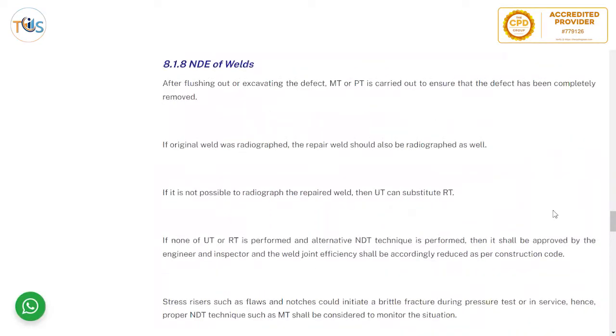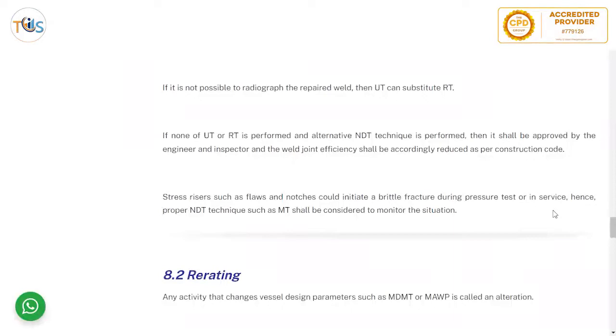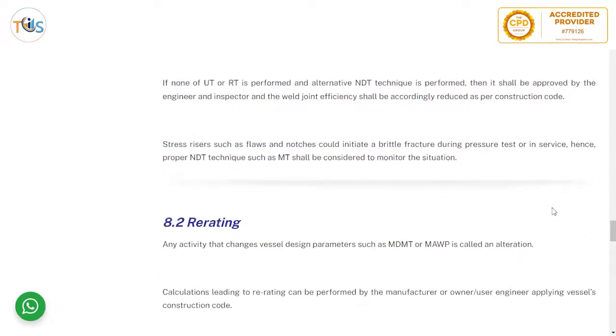After flushing out or excavating the defect, MT or PT is carried out to ensure that the defect has been completely removed. If the original weld was radiographed, the repair weld should also be radiographed. If it is not possible to radiograph the repair weld, then UT can substitute RT. If none of UT or RT is performed and an alternative NDT technique is used, then it shall be approved by the engineer and inspector, and the weld joint efficiency shall be accordingly reduced as per the construction code.